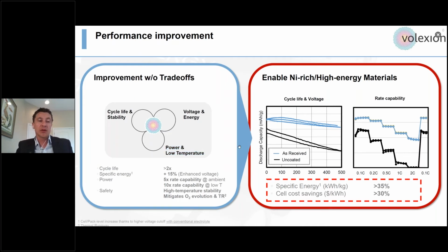So what we've observed at the scale we're at is the ability to double the cycle life, packing 15% more energy density by increasing the operating voltage, getting 5 to 10 times more rate capability, which is a power property that's desired for specialty applications in particular. And also by encapsulating the cathode material in this graphene cage, we also increase the high temperature stability, and we mitigate the runaway reactions that release oxygen and lead to catastrophic failures of lithium-ion batteries. So that's what we observe with existing commercial material.